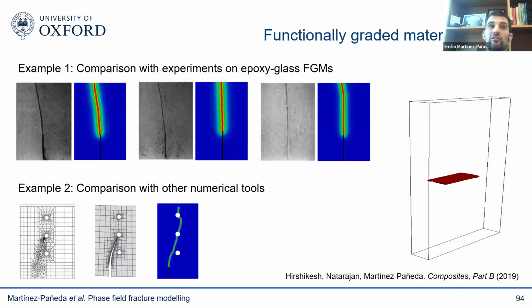So these are very interesting for phase field modeling because we don't know where the crack is going to go. So phase field gives you that flexibility of predicting where the cracks will go. And you can see some examples here. We proposed the first phase field model for functionally graded materials. You can see some examples here. Because of the mixed mode, you get crack deflection.